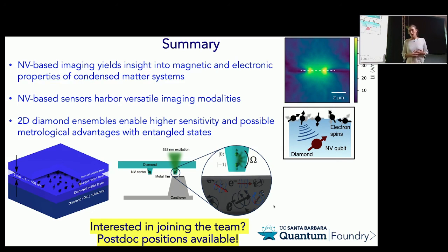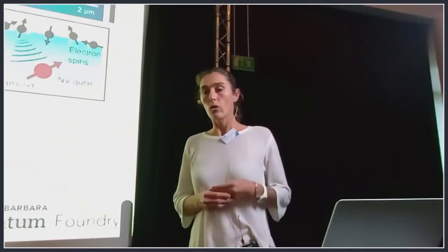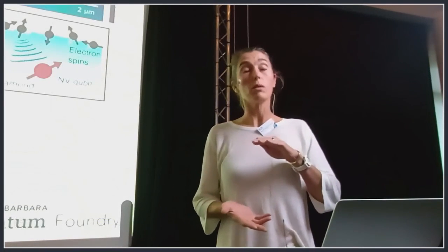Yeah, so in principle, yes, but we are looking at splitting, and our qubit splitting is on the order of gigahertz, which is effectively a DC conductivity for most systems. We can tune the splitting of the qubit between approximately 0 or maybe 100 megahertz up to maybe 10, 30 gigahertz in principle.